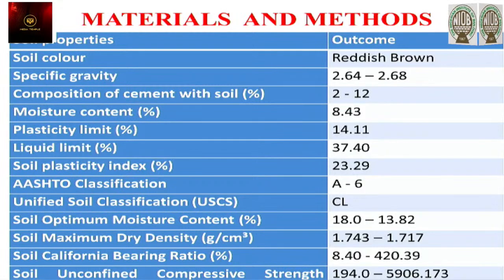Now, the materials that are required for this research are: one, the lateritic soil, Portland cement, and borehole water. Now, the lateritic soil has these properties. One is the color, which is reddish brown, the specific gravity, which is between 2.64 and 2.68, the composition of cement with soil was between 2 to 12%, the moisture content 8.43%, the plasticity limit 14.11%, liquid limit 37.40%, and so on.